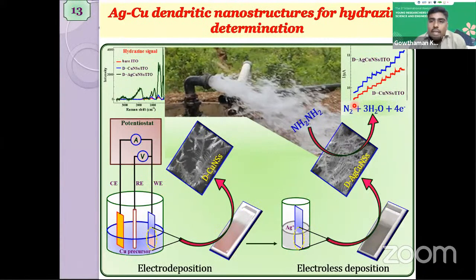So the first one is silver copper bimetallic dendritic nanostructures fabricated electrode for the detection of hydrazine. Here we use electrodeposition as well as electroless deposition. The copper nanostructures are electrodeposited on the ITO surface, and then the Ag nanoparticles are electroless deposited on the ITO surface. Combined, the AgCu dendritic nanostructures were deposited on the electrode surface, and it can be utilized for the sensing of hydrazine.